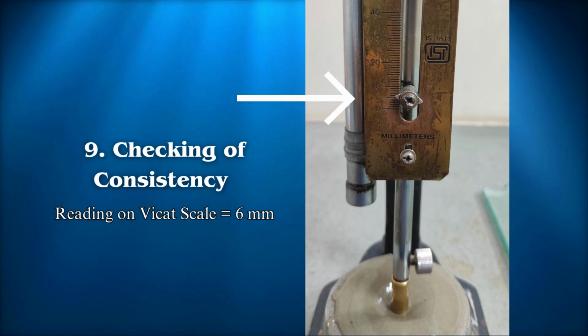If the result does not meet the standard consistency, you can make adjustments to the water percentage and repeat the test. Continue this process until the standard consistency is achieved, which allows the Vicat plunger to penetrate to 5 to 7 mm from the bottom of the Vicat mold during the test. These steps will help you perform the consistency test for cement accurately.